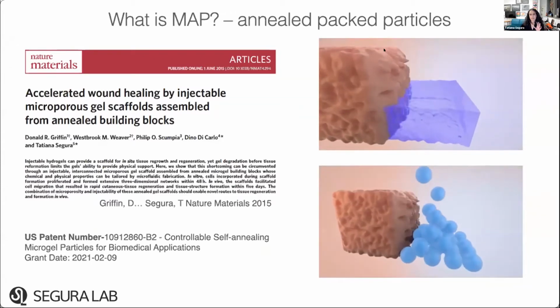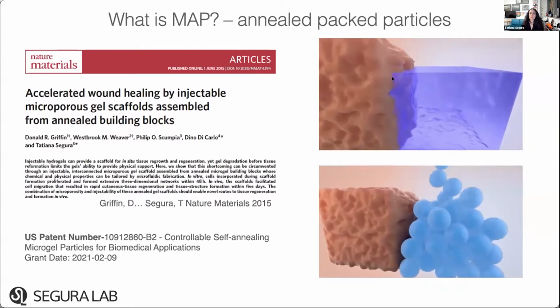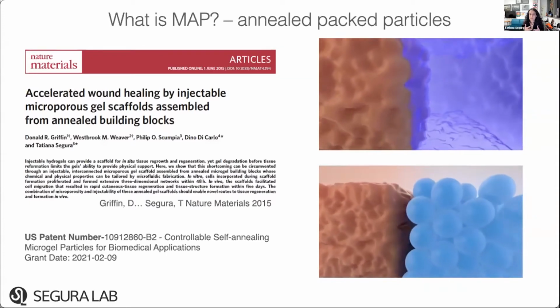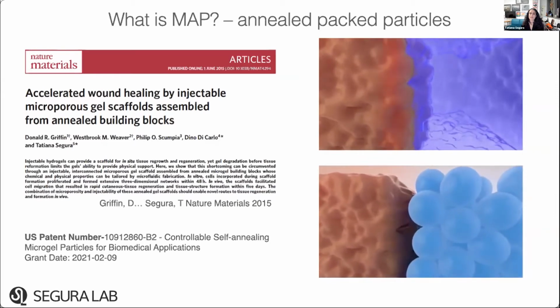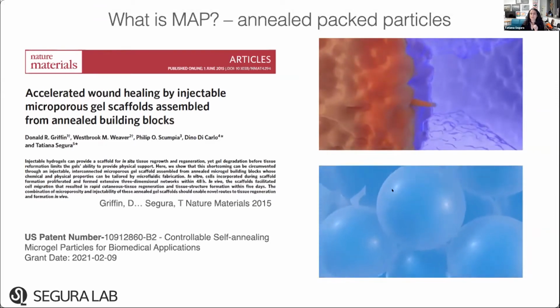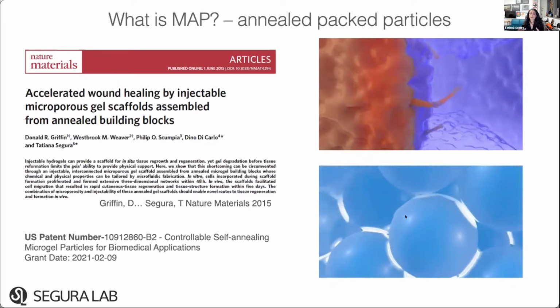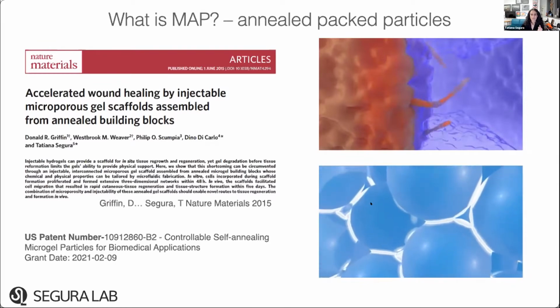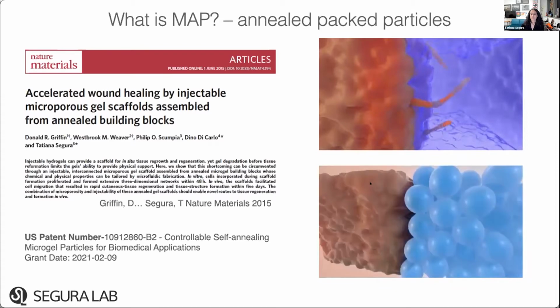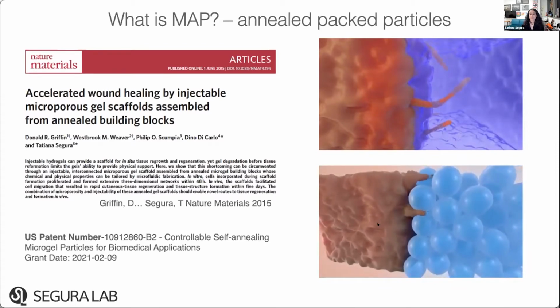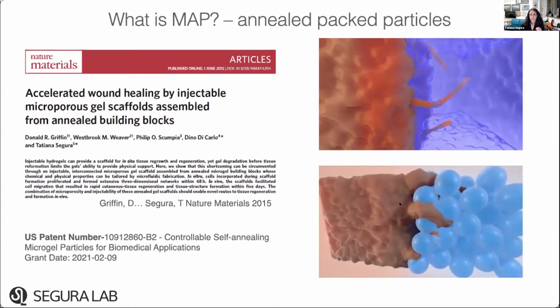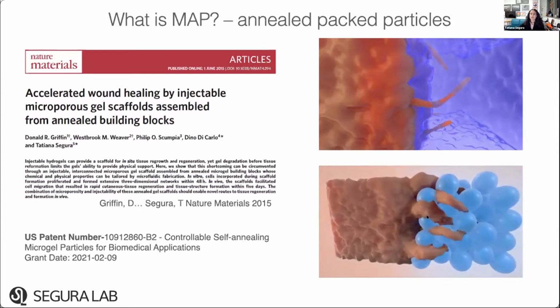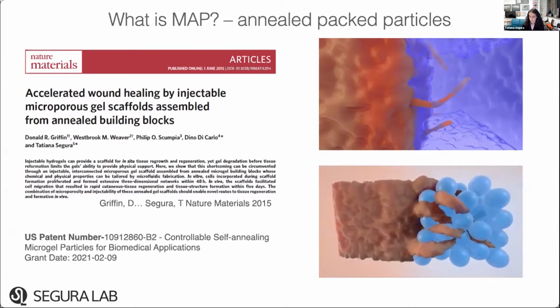But basically, in the tab here, this video is showing the previous material, that is just polymers interlinked with each other. We have now decided to make the same gel, but now into beads. These beads are going to pack and leave behind these openings that allow for rapid cellular infiltration because they're large enough. So if you match the size of these pores to the size of the tissue that you're trying to infiltrate, you actually get much better repair and regeneration just by having this porosity. And because they're beads, they're actually injectable, which is really important for our brain work.